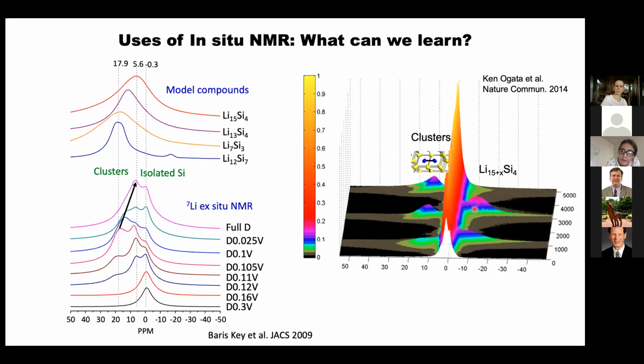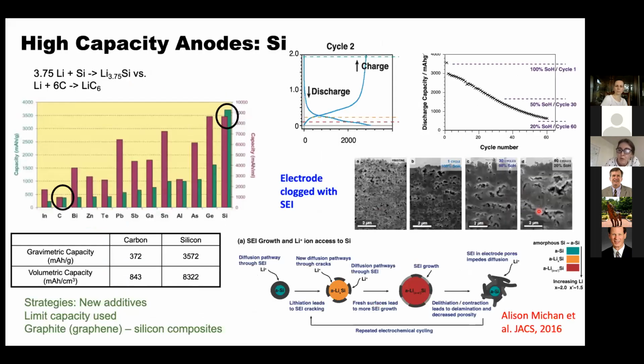And what we were seeing back in 2009 was the first evidence of this problem that I show you here, that the silicon is so highly reactive, it continues to eat the electrolyte up and just form this horrible mess of decomposition products that gradually eat lithium from the cell and result in a reduction of capacity. And so the challenge now is to add additives to mitigate this reaction.